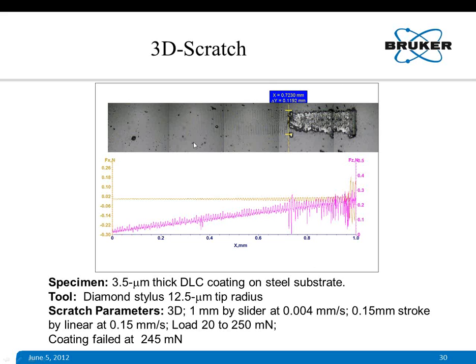This type of test, 3D scratch, is very helpful when the coating is really thin and the substrate is soft as well. And this was done on a DLC coating on steel substrate using a 12.5 micron tip radius diamond stylus. From this graph, we have an Fz plot, and we can find out the force, the critical load, for failure of this coating.